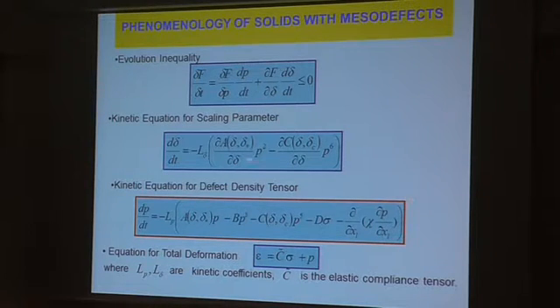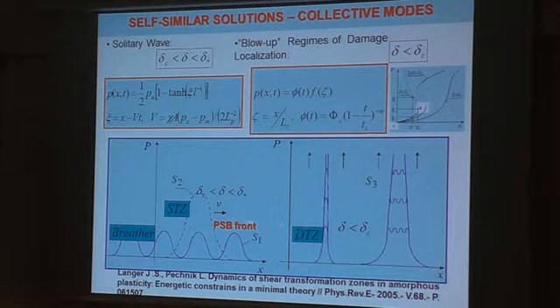And it was derived equation for these field variables, and study of characteristic nonlinearity of group properties of this equation allowed us to establish that there are two types of similar solution related to metastability area: a solitary wave with the front corresponding to multi-scale transformation in dislocation substructure. But if we pass another critical point, this similar solution is transformed into a specific similar solution with blow-up nature. It means that over the scales, that is the characteristic value in self-similar solution, we have a blow-up region.